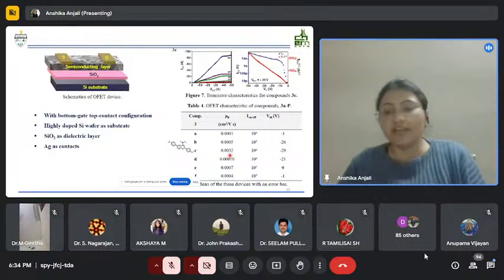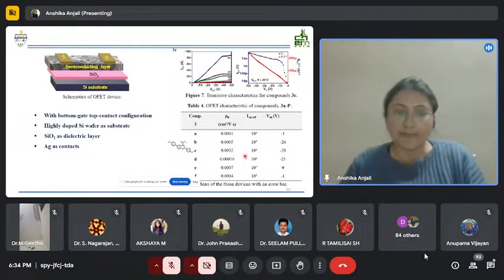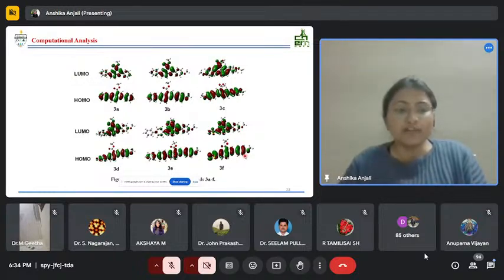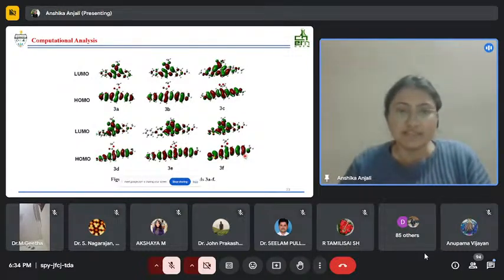So the highest hole mobility here was observed for dimethoxy substituted compound 3C with the hole mobility of 0.0032 centimeter square per volt per second. It does show an on-off ratio of 10 raised to power 4 with a threshold voltage of -29 volt. So all these experimental data were supported by our computation analysis.